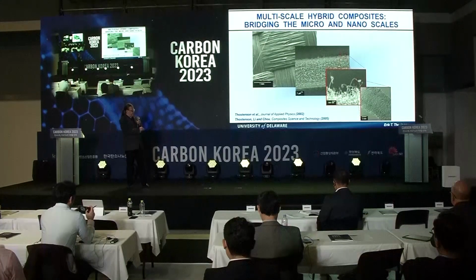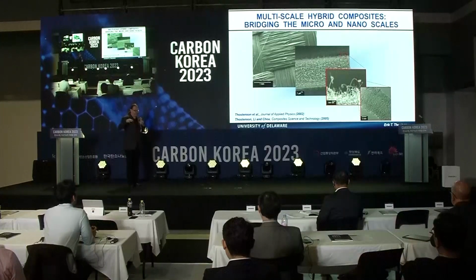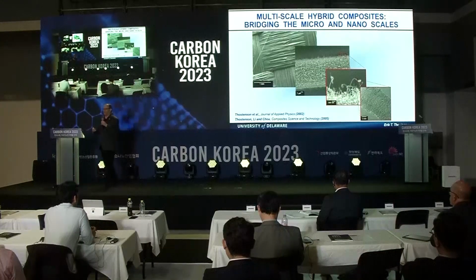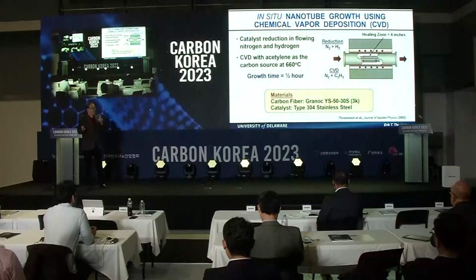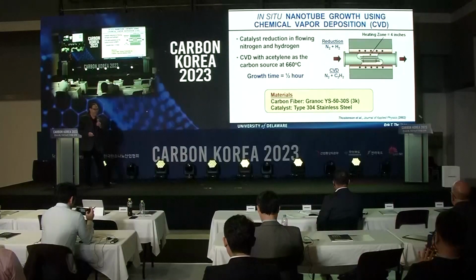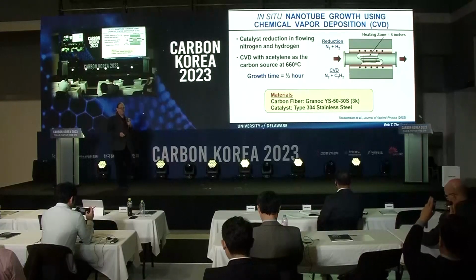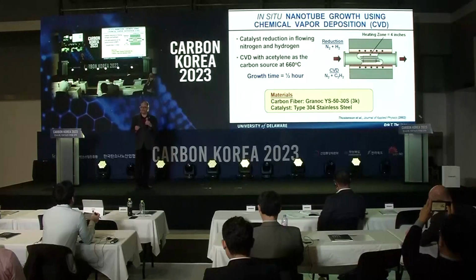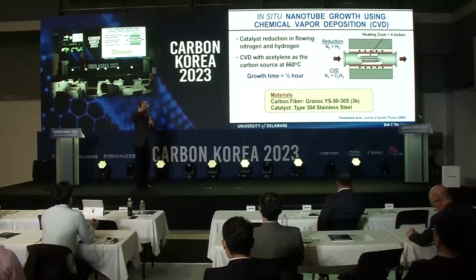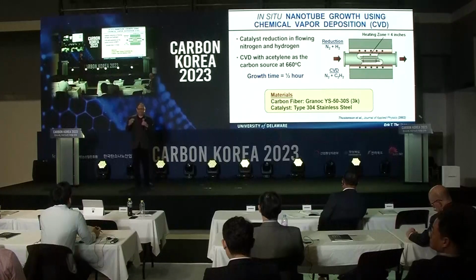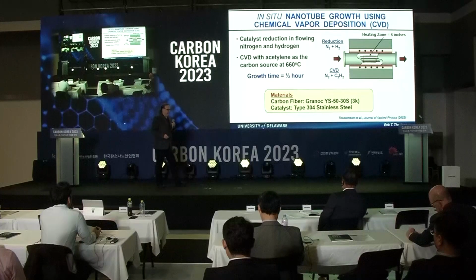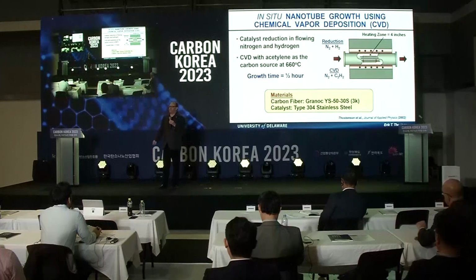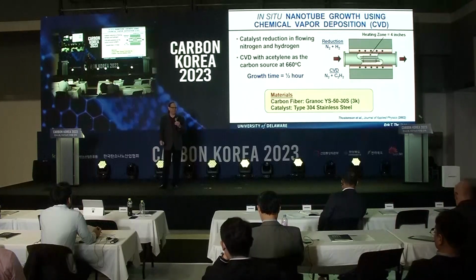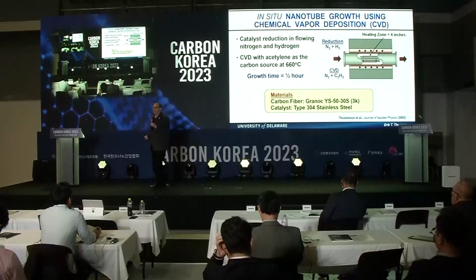What we were first doing is looking at growing the nanotubes directly using chemical vapor deposition. But this is a very energy-intensive process. It only works on a few fibers, in particular high-temperature fibers. And while it's somewhat scalable, I didn't really see it as something that was going to make a big impact. So my interest was, well, can we combine these reinforcement scales using a different technique?